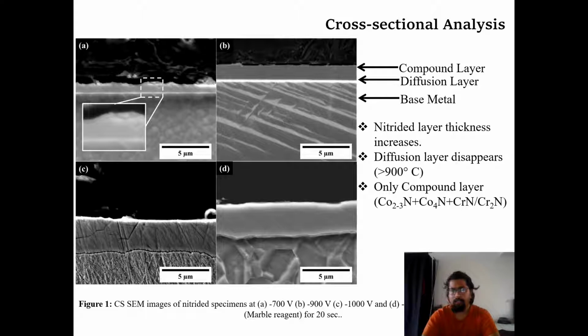So this is what the nitrided layer looks like after HIPIMS discharge. The first is -700 volt, where the other parameters we are keeping the same, such as base pressure, which is 8.3 × 10^-3 millibar, temperature, which is 400 degrees Celsius, and power during the whole experiment, which is fixed at 1 to 2 kilowatt.